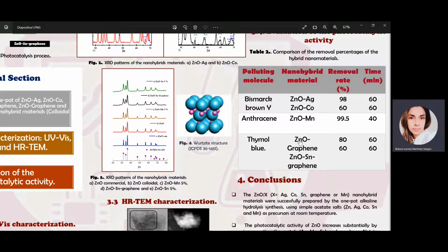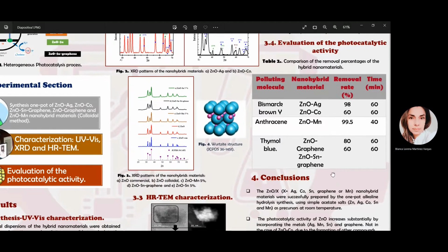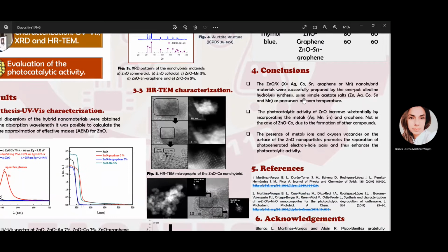In this case, when using these materials, the model molecule used was Bismarck brown V, and these are the values of the removal rate. At the same time, one of the conclusions of this work is that zinc oxide with different metals such as silver, cobalt, tin, graphene, or manganese nanohybrid materials were successfully prepared by the one-pot alkaline hydrolysis synthesis.